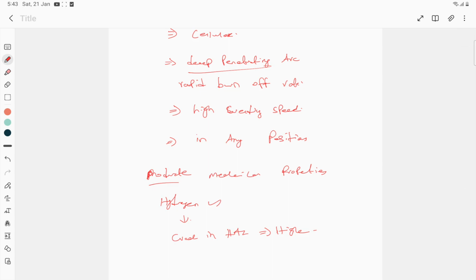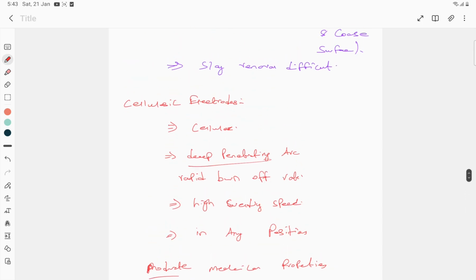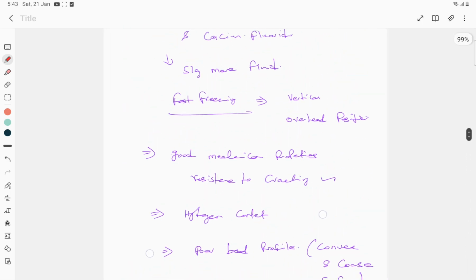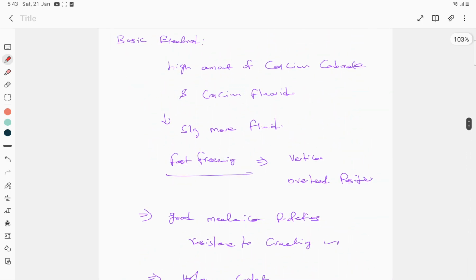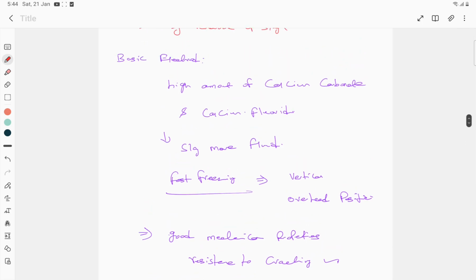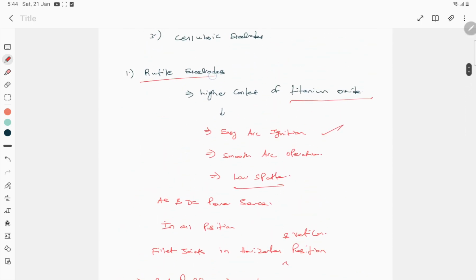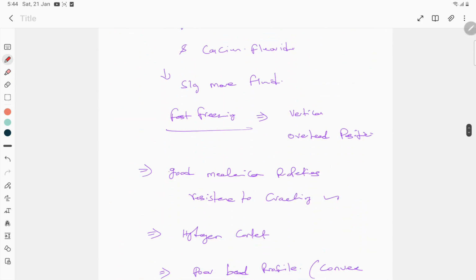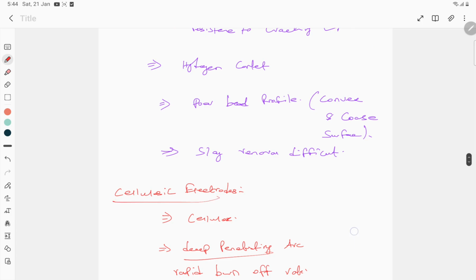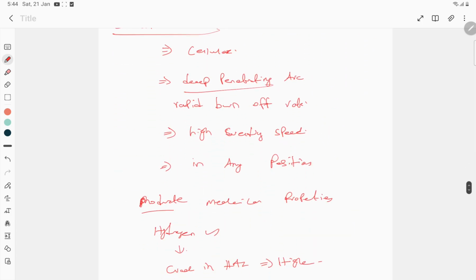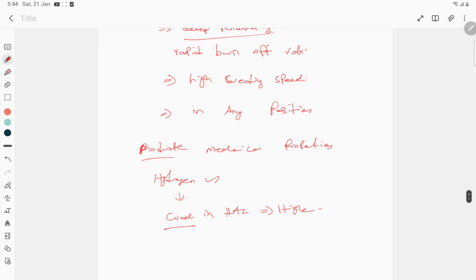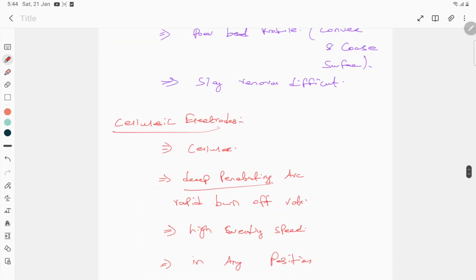Okay, so these are all the main classifications. Under this we have many more subcategories. So what we have seen in this video is that the flux coating changes in different types of electrodes. Mainly we have three types. One is rutile, then we have basic, and finally we have seen cellulose. Finally we have seen that it can be used in all positions, and we can get very good penetration. High speed is also possible. One major disadvantage is that hydrogen content will be very high. As a result of that, there is a possibility of cracks in the HAZ.